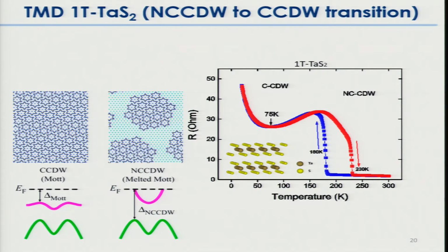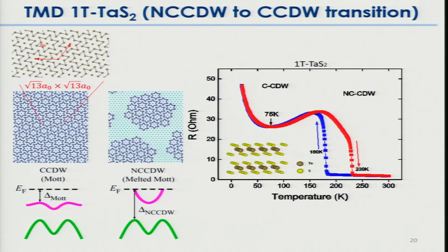And then as you go down to lower temperatures, the resistance goes up and it becomes a Mott insulator. It converts to a commensurate charge density wave from a non-commensurate charge density wave. The melted Mott stage has the Fermi level going through the conduction band, and here's an energy gap. So this is definitely an energy gap material at low temperatures. The interesting thing about this material, and it's been studied by lots of people, is it has these beautiful formations they call Star of David in the melted Mott state.